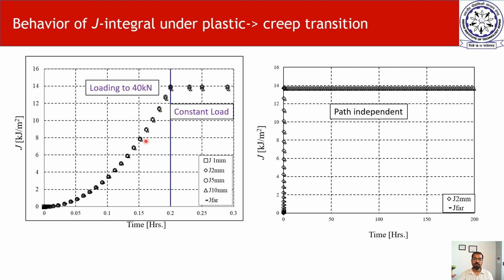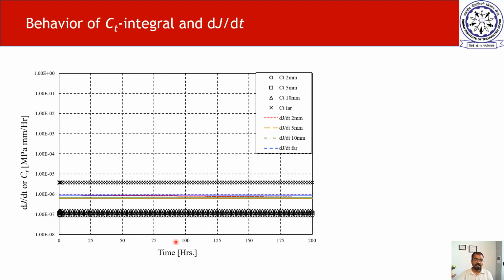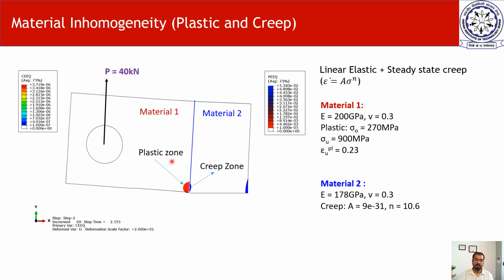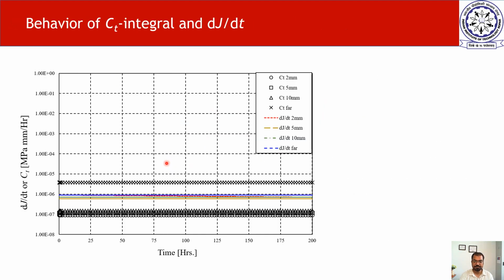So this is the loading step where we apply the force of 40 kilonewton, and then we keep the force constant, and you see that the J integral is path independent in this case also. And C integral is also showing path independence except the far field C integral, but the problem is that C integral is not taking into account the plasticity of material 1. So that is not included in the formulation of C integral because it only takes care of the creep strain term.